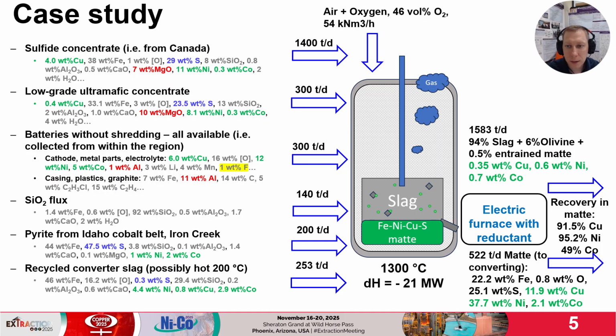The matte contains quite a lot of copper by concentration. Iron in matte will be removed in the converting that can be done in typical Peirce-Smith converters. The gas should be cleaned from dust. It will likely need quenching to wash away chlorine and fluorine. Unburned plastics can be an issue, requiring good afterburn on the furnace exit.